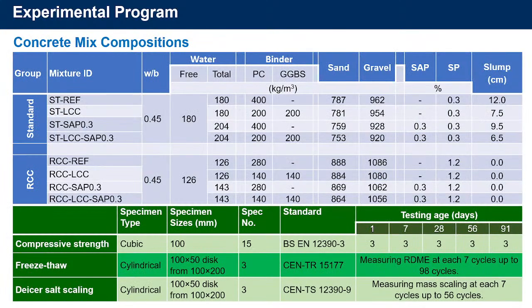I developed 8 different concrete mixes in this study in 2 groups: standard and roller compacted concrete. In each group, I have a reference concrete with 100% Portland cement. The second mix is the one where 50% of Portland cement has been replaced with GGBS to consider the effect of low carbon materials. The third mix is the one where 0.3% of superabsorbent polymers has been used to develop SAP-modified concrete. And the final mix is a combination of 50% slag along with 0.3% superabsorbent polymers.